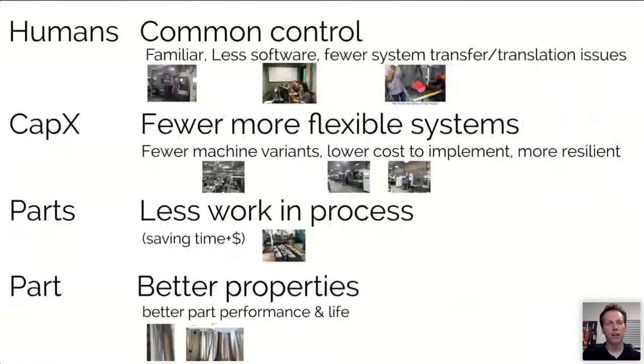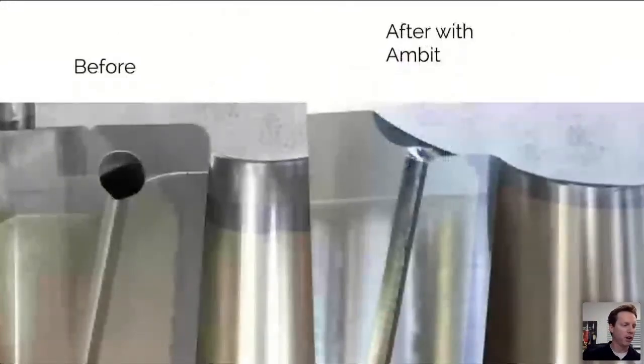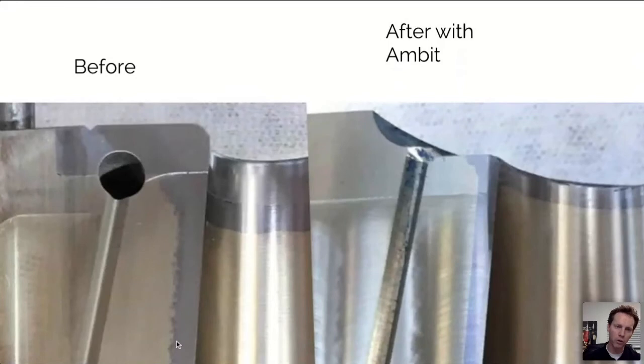And if we look once again at this set of scales and domains and go to part level, you'll look here on the left. We've got a before and an after shot. If you look at the weld here in the before, you'll notice that it's somewhat ragged. This is an indicator of how much heat input and how much that metal mixes in that dilution area, and consequently it has quite a large heat affected zone. Over here on the right with Ambit, it's a laser-based process. You can see it's a very nice straight line by comparison, and it's a much, much smaller dilution zone and heat affected zone. And that then bodes well for its future life, where not having that zone, which is susceptible to other things, can dramatically increase its lifetime.